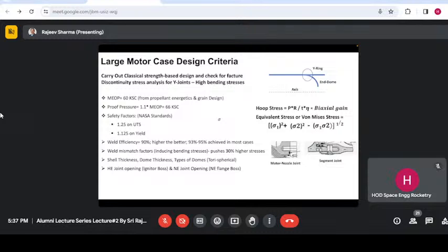The weld efficiencies had to be understood. The design weld efficiencies were 90%, but we actually achieved more than 93 to 95%, in some cases 98%. The weld mismatch factors are very critical.